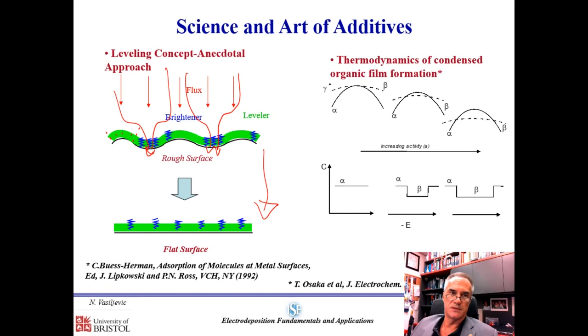Of course, this story is not really supported by much scientific evidence, and the real story is way more complex. The bottom line is that we consider using some organic substance as an additive. It has to adsorb on the surface, and one of the signatures of the adsorption process of the organic substance is the creation of this capacitance swell, which broadens out if we increase the concentration of the additive in the solution.